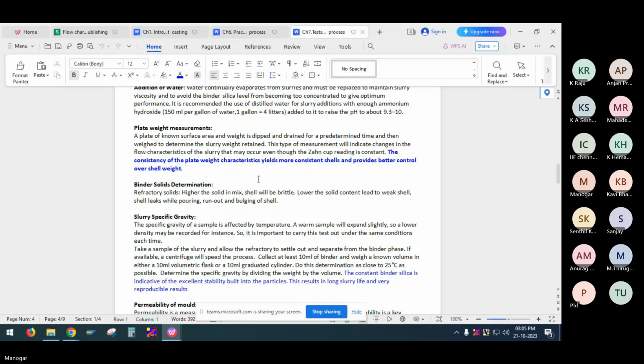plate weight measurement. The consistency of the plate weight yields a more consistent shell and provides better control over shell weight. Because the shell weight is important for the casting and also for the cooling and shell breakage or knockout properties. So once in a while you can check whether the shell thickness is coming uniform or not. That is the test where we can confirm through plate weight measurement. Then binder solid determination, refractory solids: higher the solids in the mix, the shell will be brittle. Lower the solids, the shell will become weak. Then you will have leaks and runouts or bulging of shells.